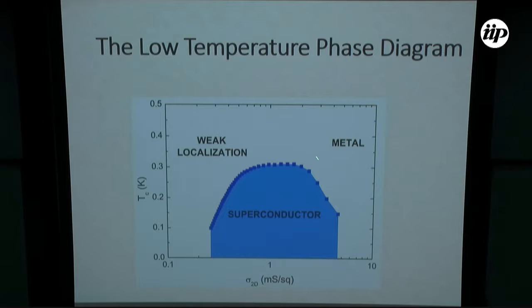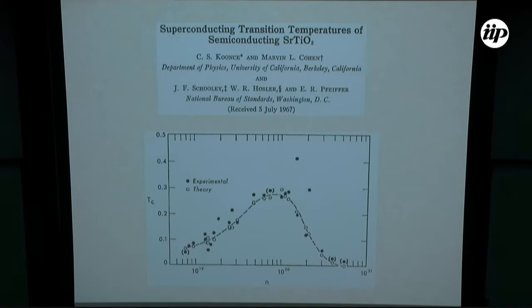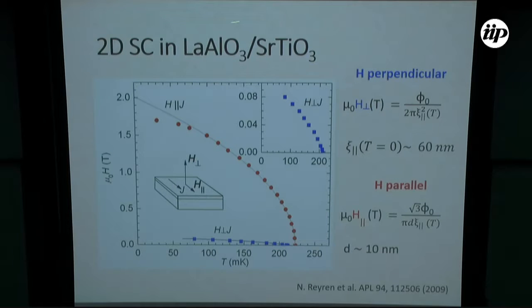Now, anyway, this dome-shaped behavior may remind you of the result of 50 years ago by Koonce and Cohen about SrTiO3, the semiconducting compound that undergoes a superconducting transition at the same temperature, around 300 millikelvin, where here you see TC changing as a function of 3D carrier density. So again, you have an increase of TC to a maximum and then a decrease. And so are the 2 domes correlated or are they different? So what we can say is that the dimensionality is different. So for the interface, we are in a 2D superconducting system.